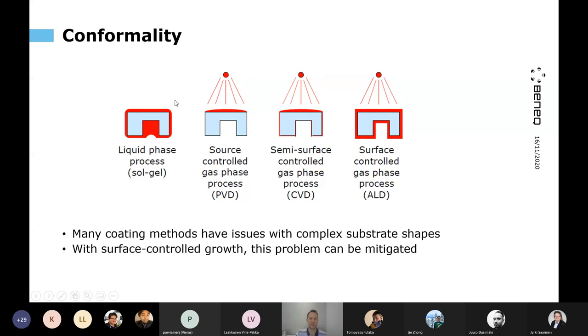Whereas in other techniques, some are conformal, like liquid phase processes. So you dip it somewhere and you get it coated everywhere, but coating is far from uniform, and it may be difficult to coat some smaller pores and holes of the parts. And if they get coated, then the liquid may stay there, and you get a lot of excessive film growth there. Whereas the so-called source-controlled or line-of-sight methods, such as typically PVD methods, sputtering, evaporation, tend to coat the side of the object that is towards the source, but not the other side.